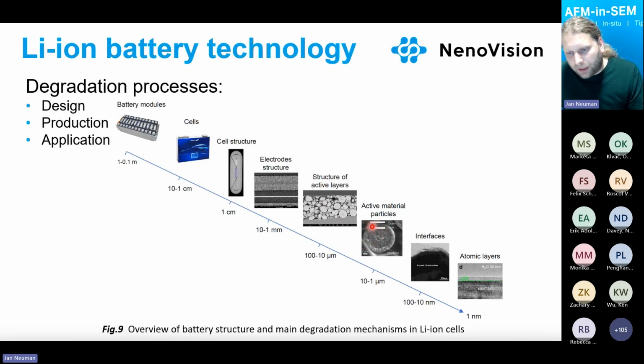In this case, we can see particles with a core-shell structure. So there are different ratios of nickel inside the particles and outside. During the cycling, there can also be some diffusion of nickel ions or manganese dissolution.